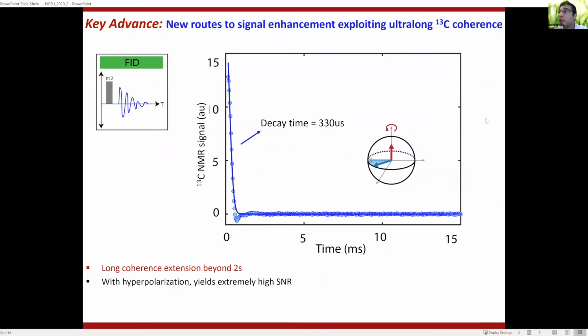I also want to show some very interesting new results out of these particles, or out of the system. All the results that I showed so far is a classic pi-half acquire of free induction decay. So all the signals that I showed, they are hyperpolarized, they are very large signal. But what you're doing is a single pi-half pulse, the spins precess in the magnetic field, and you're collecting the fluorescence, you're collecting the free induction decay.